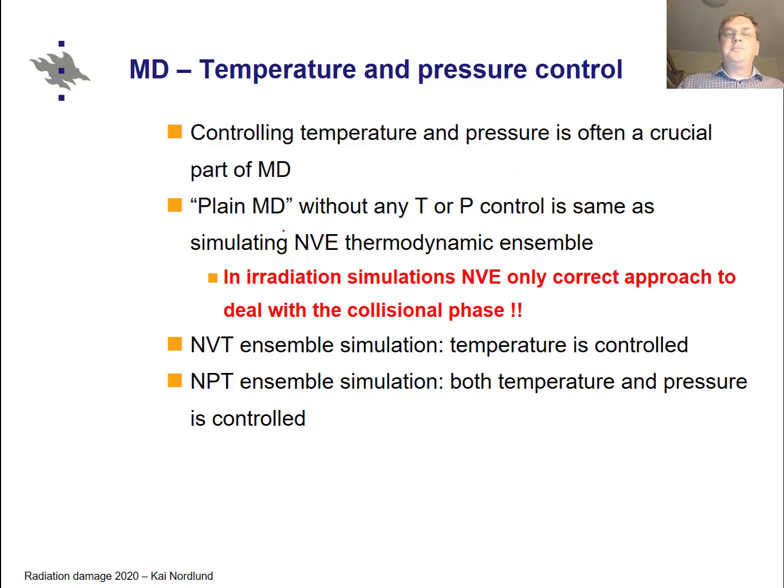Well, then in many molecular dynamics simulations, there is what's known as temperature or pressure control. So if you want to simulate in thermodynamic equilibrium a system with constant temperature, then you simulate the NVT thermodynamic ensemble and control the temperature. If you have constant pressure, then you can similarly simulate the NPT using a pressure control algorithm and also temperature control.